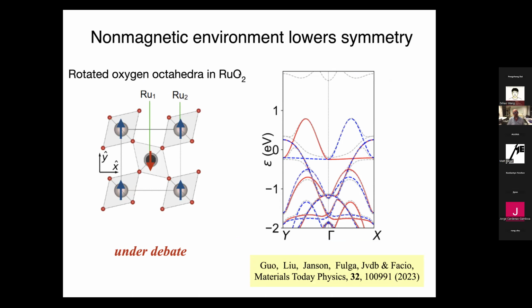And the real material, one of the first real materials that was considered in the field, was ruthenium dioxide. It's a bit unfortunate because it turns out that in bulk it actually has zero magnetization, or if it has a magnetization, it's tiny. So therefore it's not magnetic. But if you look at its structure, it's perfect for an altermagnet. It has two sublattices. This is a rutile structure. And the two sublattices are related to each other by a 90-degree rotation of the oxygen cages, as you can see here. And at the same time, there's antiferromagnetic order.